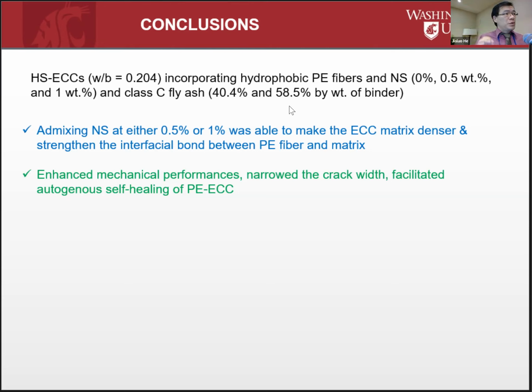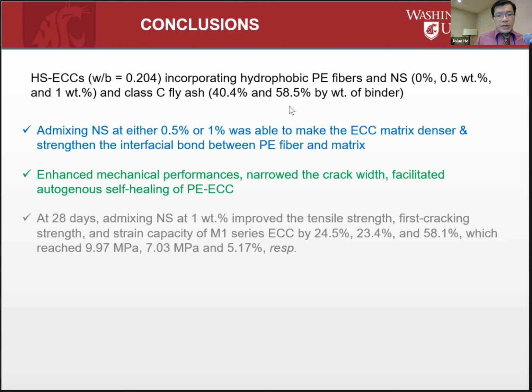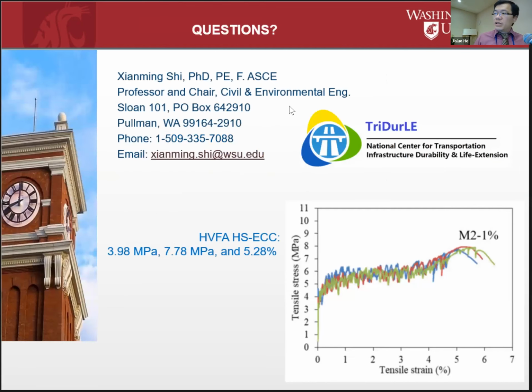And the healing products were actually different when we characterized the high volume fly ash one, because when the cracks were narrower, the product was mostly CSH. But with the wider cracks, the product was mostly calcite. So we're seeing this kind of behavior. And what really intrigued me, honestly, is this one, the high volume fly ash one, because you are achieving a greener binder, high strength ECC, and really beautiful self-healing behavior.